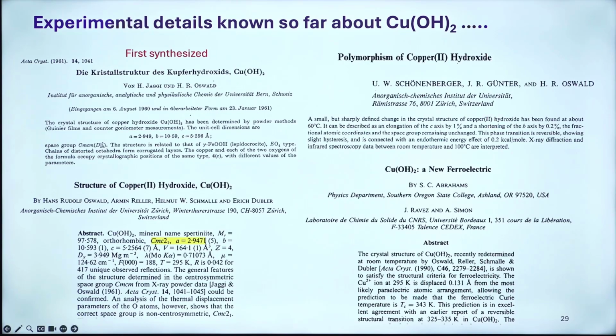So this was the motivation for us. The interesting point is that this copper hydroxide is also magnetic. Normally, like superconductivity and magnetism, is it possible to have a coupling between magnetism and ferroelectricity? That we call a multiferroic, where a magnetoelectric coupling is present. That was another motivation for us. First we thought about the magnetism of this copper hydroxide, and then this proposal from experimentalists came that this could be a ferroelectric. This combined effect motivated us to see if we can understand this in a much better way.